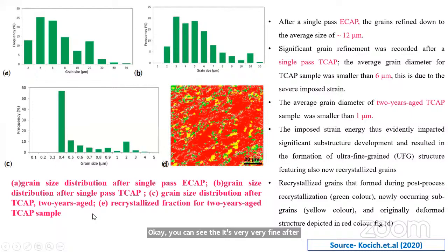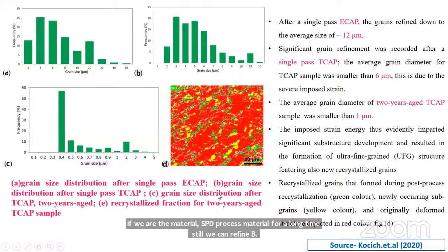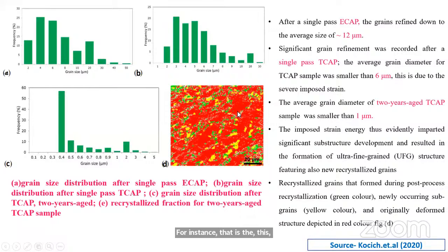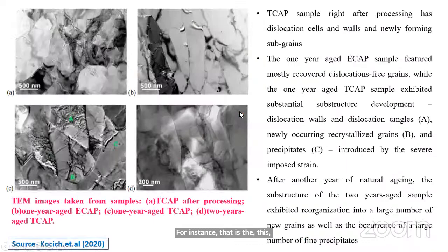And E is the recrystallized fraction, but the diagram is not here. So this is D, the recrystallized fraction for the 2 years aged TCAP sample. After recrystallization, you can see the grain sizes are oriented. This is the effect of aging. If we age the SPD processed material for a long time, we can still refine the grain size, because grains are recrystallized. After 2 years aging, this improves the strength of the material.